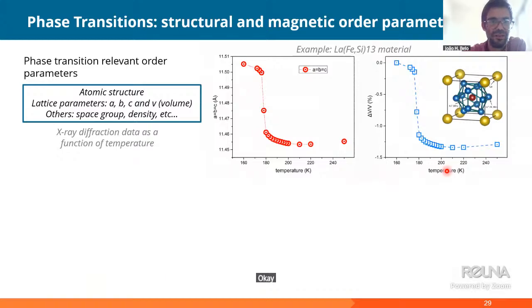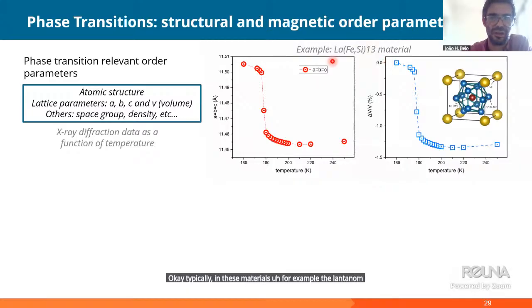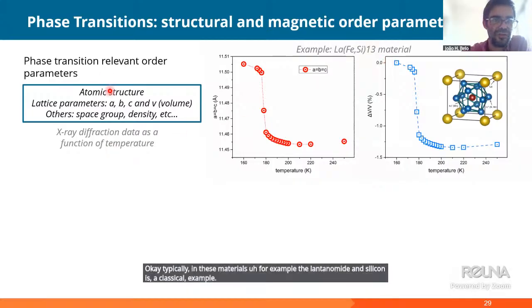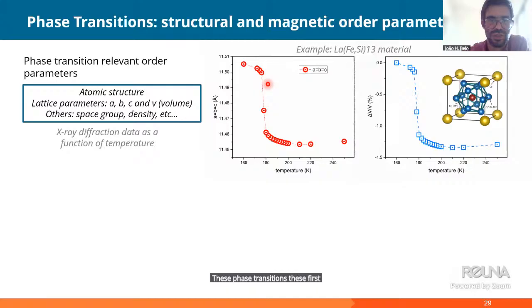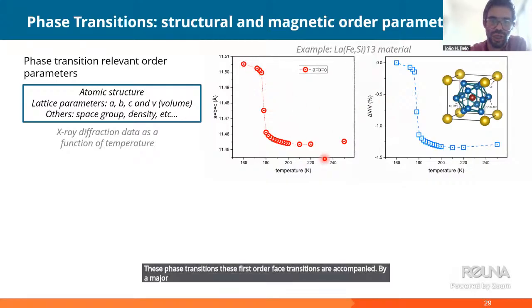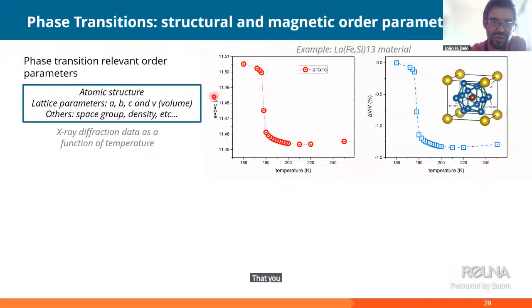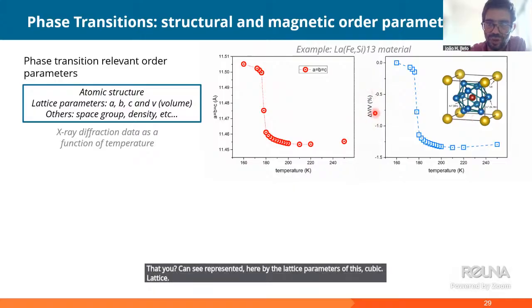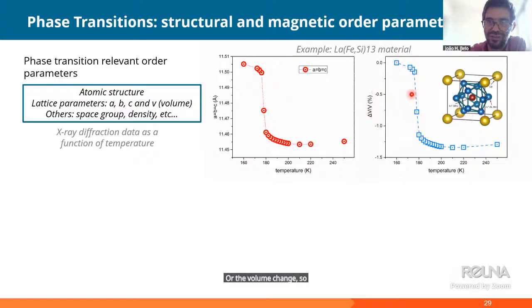Okay, typically in these materials, for example, the lanthanum iron silicon is a classical example, these first order phase transitions are accompanied by a major structural change that you can see represented here by the lattice parameters of this cubic lattice, or the volume change. So this material presents a negative thermal expansion as it contracts about 1 to 1.5% on warming up or when applying field.